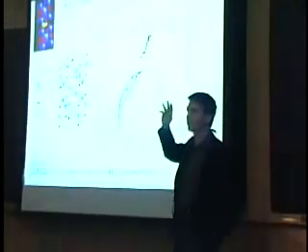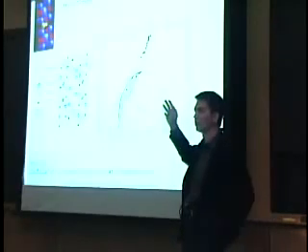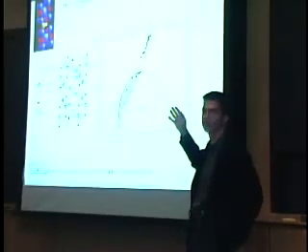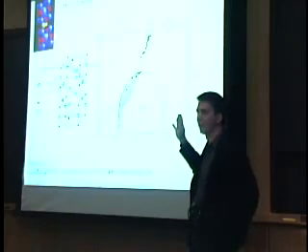which probably most of you are familiar is a fairly well-known high-temperature superconductor. And the critical issue, or one of the critical issues, was how the material behaves as a function of oxygen content. Essentially, that Z up in the formula can go anywhere from 6 to 7. And at 7, it's a high-temperature superconductor. At 6.5, it's a low-temperature superconductor. And at 6, it's an antiferromagnet. And so figuring out what the phase diagram looked like was, I guess, worth the PhD thesis.